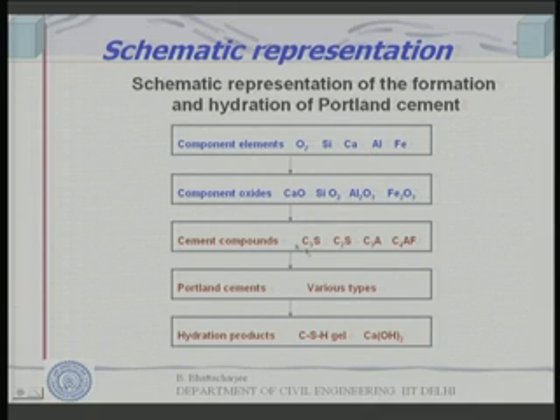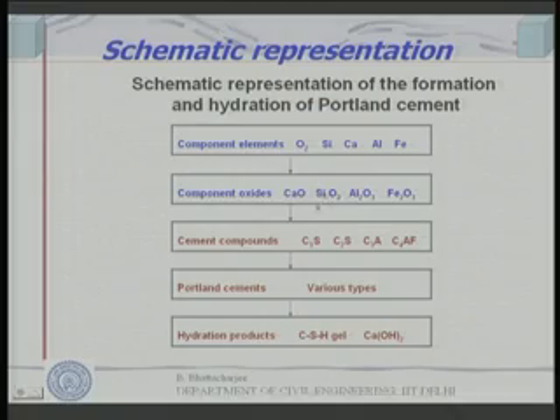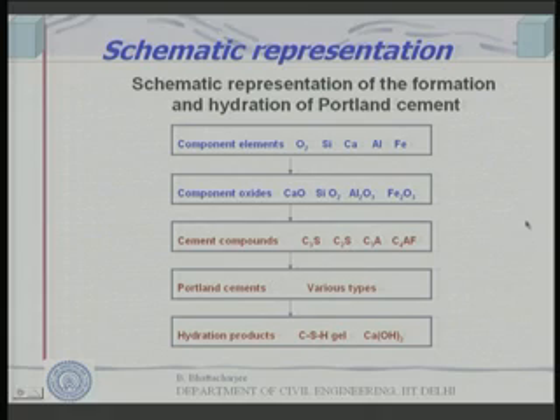Now, these combinations can differ in different types of cements. The proportions of these would vary, and by varying these proportions we can actually get different types of cements. Again, we will discuss this in detail, because I can control the proportions of oxides. The oxide composition of the cement can be controlled relatively from the raw material mixing etc., and thereby the compound composition of the cement can be controlled. And we know the properties of each of them, like I mentioned that C3A possibly reacts before anything else, because it has the highest heat of hydration. So, if I want to reduce the rate of heat of hydration, then possibly I will have to reduce the C3A compound in the cement.